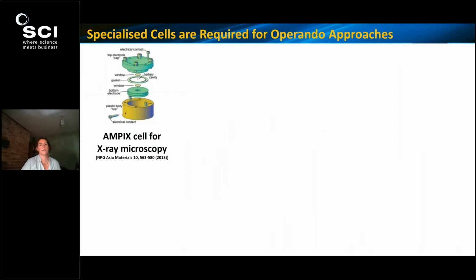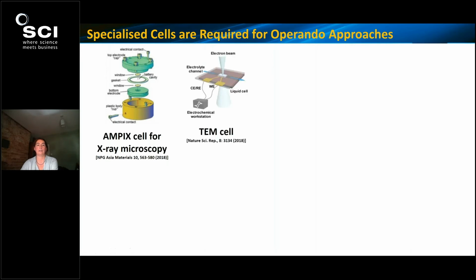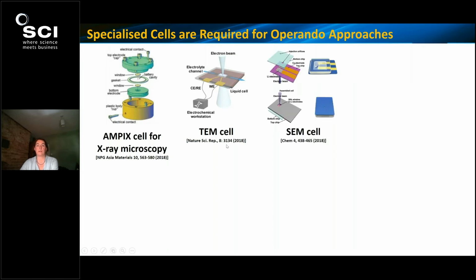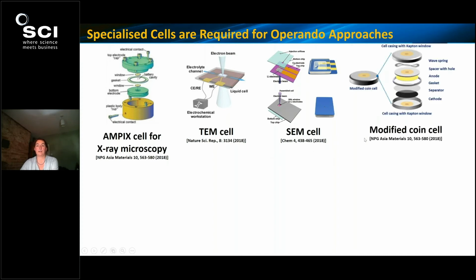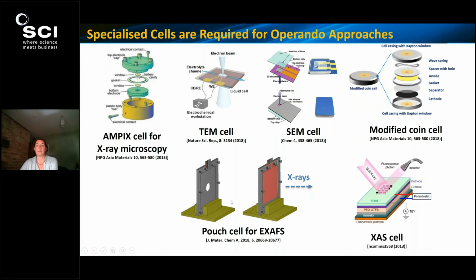But they can be quite challenging techniques to do well because they all involve bespoke cell types to allow for the simultaneous analysis and electrochemical activation of the contents. So this is just a snapshot of various different types of cell used for various techniques. X-ray microscopy would use a cell like this AMPIX cell. For TEM, obviously you need to be able to transmit an electron beam through the entire cell, so you'll need an appropriate window. And most of these cells, whether they're for X-ray, TEM, SEM, or other generalized coin cells and pouch cells, all need specialized windows to allow X-rays, electron beams, or RF energy through, and to be connected up to potentiostats to be able to detect and analyze the desired changes that occur within.